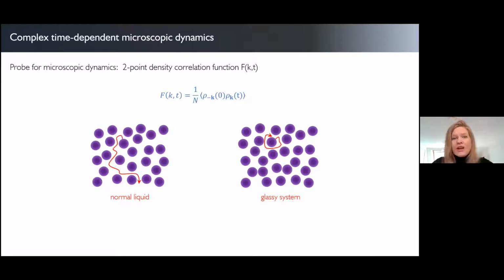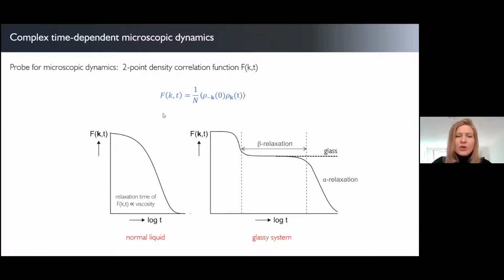And to give you an idea what these functions look like, for normal liquids, particles can move around very easily, so they quickly forget where they were some time ago. And that translates to a very rapid decay of this density correlation function, a decay to 0. And the typical relaxation time, so the decay time at which this function decorrelates to 0, is also actually a measure for the viscosity. So this is for a normal liquid, but for a glass forming material, the picture is much more complex. And in particular, we often see a plateau developing here at intermediate timescales, which can actually extend over many, many decades in time, so many orders of magnitude.